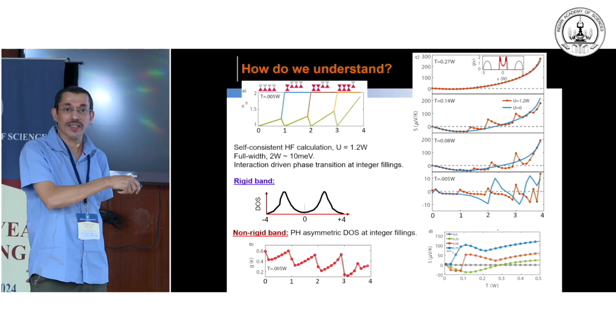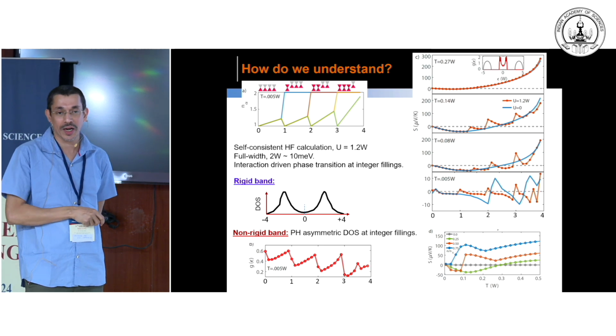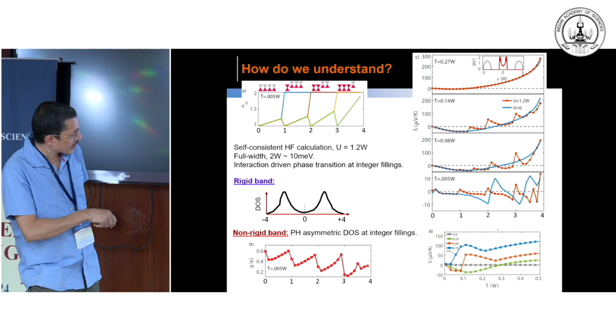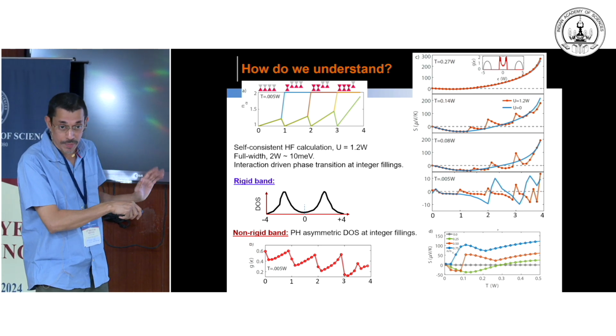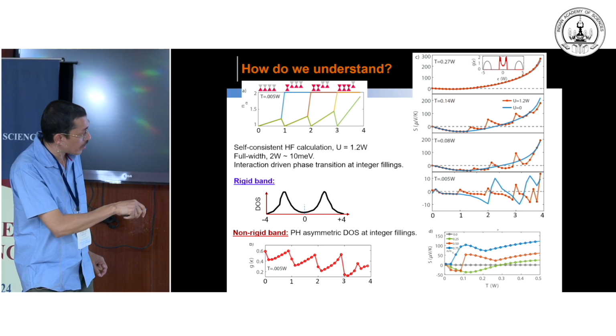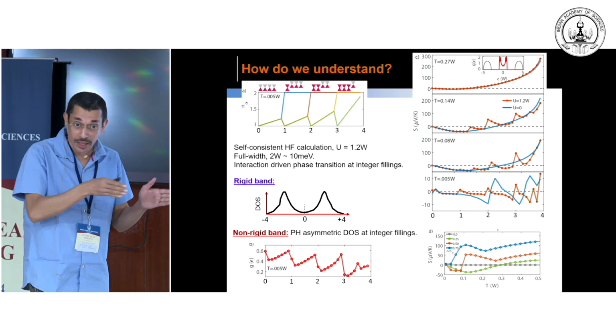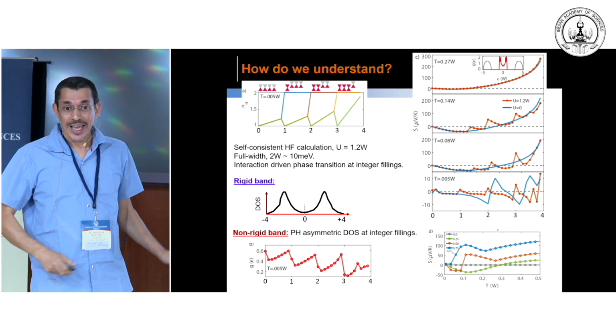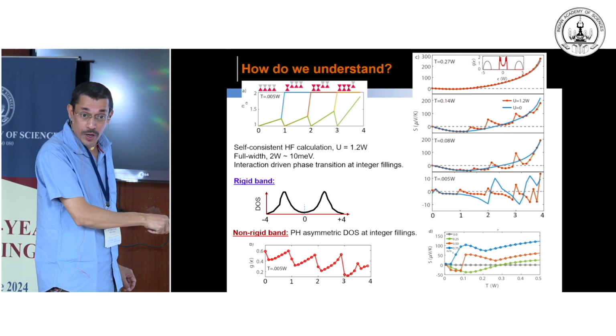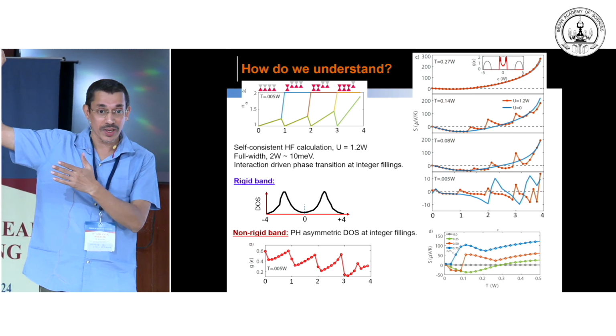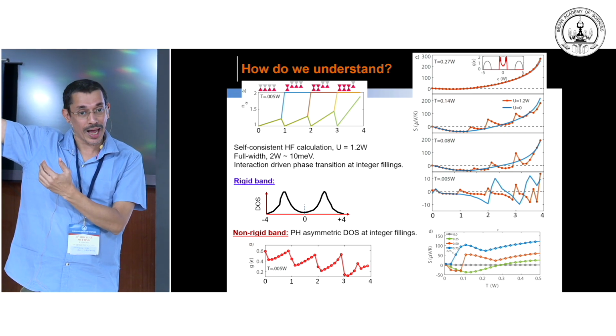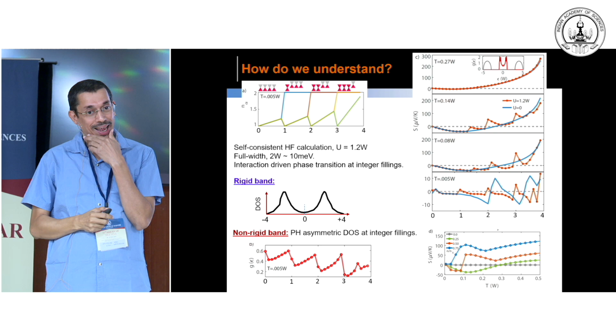I see. Okay. So what I am trying to say, the single particle picture actually cannot describe this physics; you need correlation physics to describe it, and the point is the particle hole asymmetry. Because even if you have a large density of state, for example, if you have the Fermi energy here and your system is particle hole asymmetric, the Seebeck coefficient still can be 0, even if you have a large density of state at this point. Even if you have large effective mass or large density of state, you do not have correlations. It's basically the correlation function of entropic current and electric current. Right. That's exactly right. Okay. Right. Let's discuss that.